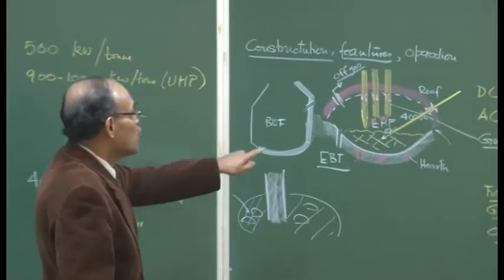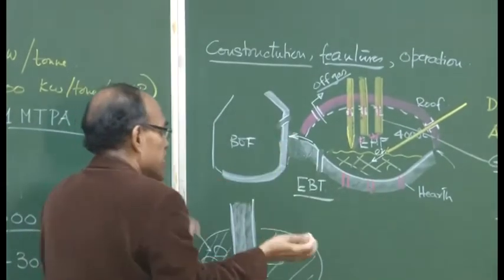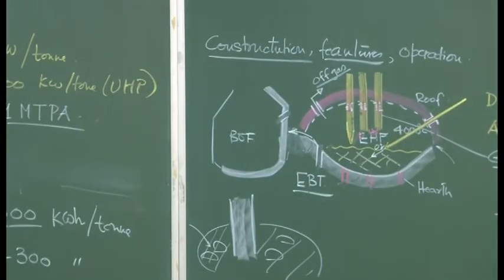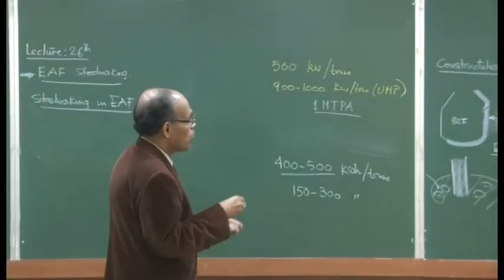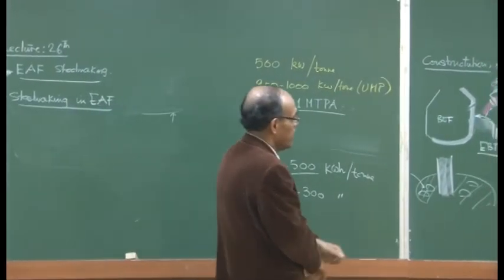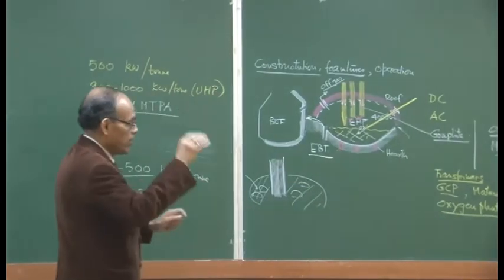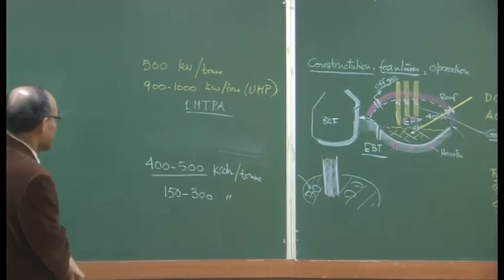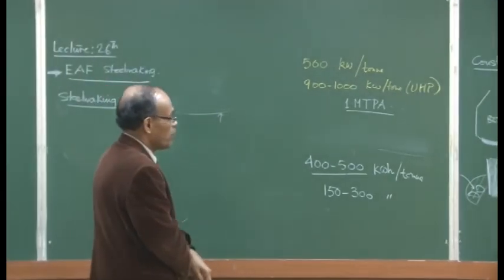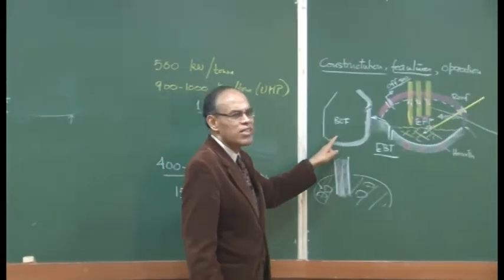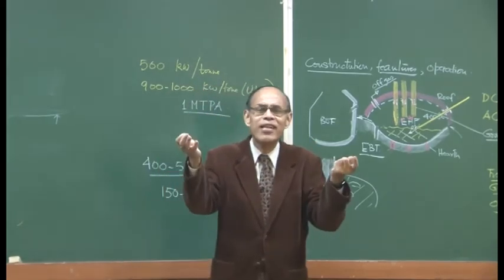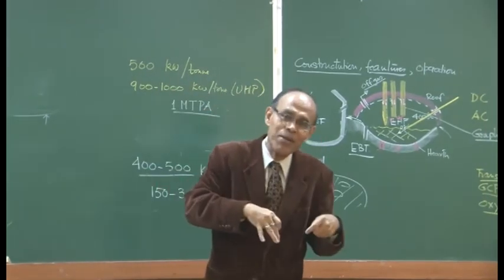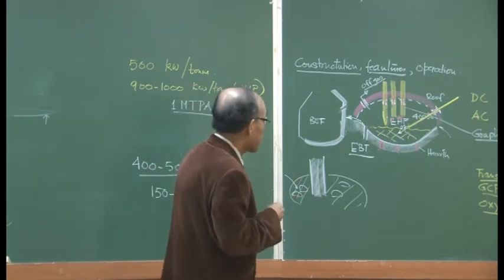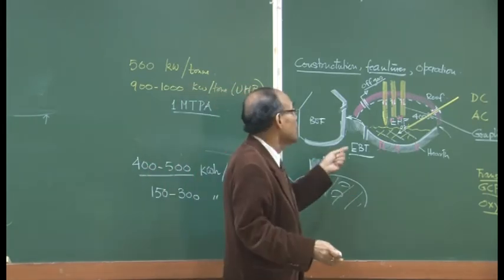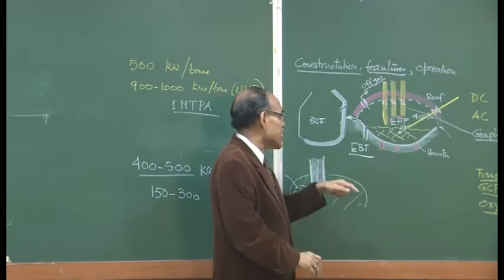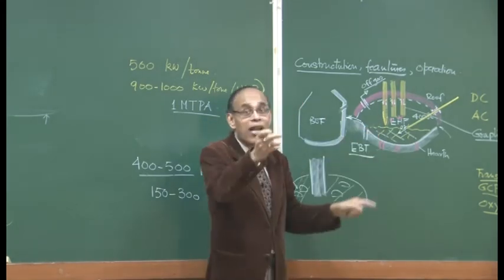Why there is an EBT and we do not tilt the furnace to tap molten metal, that will be discussed later on when I deal with the tapping operations and the role of the oxidizing slag in the performance of subsequent steel making processes, particularly the secondary steel making processes. So, the heat preparation per se need not be discussed. Okay, it is the same thing that once heat is made, you inspect the furnace, if there is some kind of a damage, and then you repair that, and then you make it vertical, or you make arrangements for charging of the material. You charge the scrap is going to be charged, as I said.